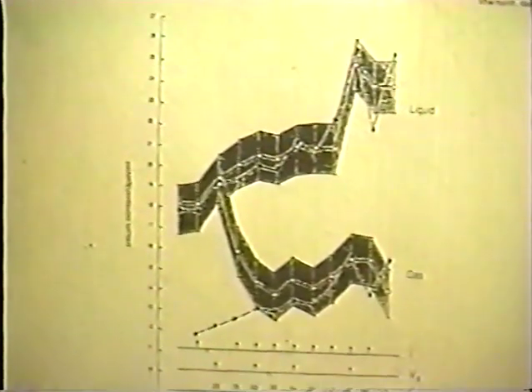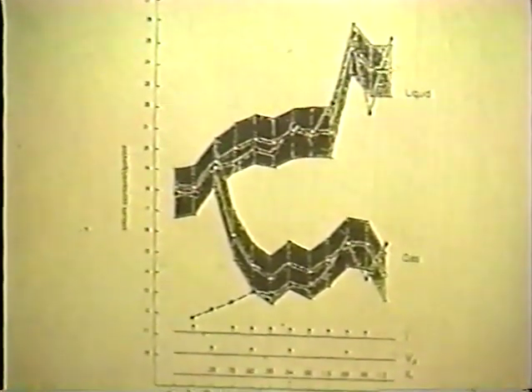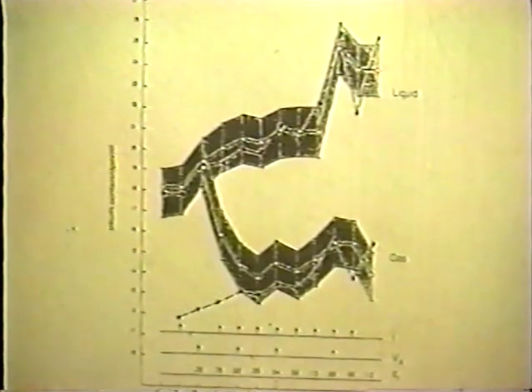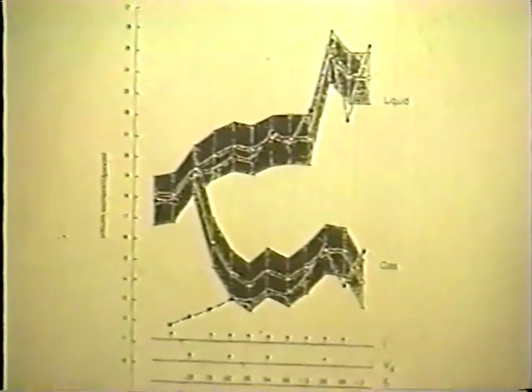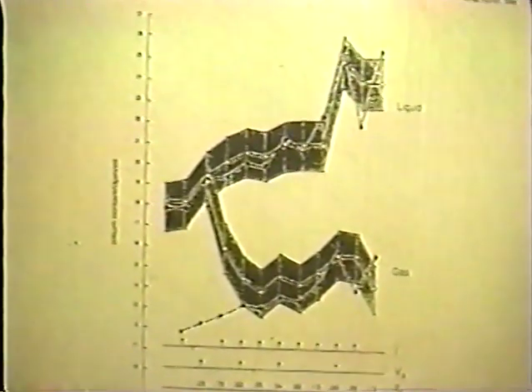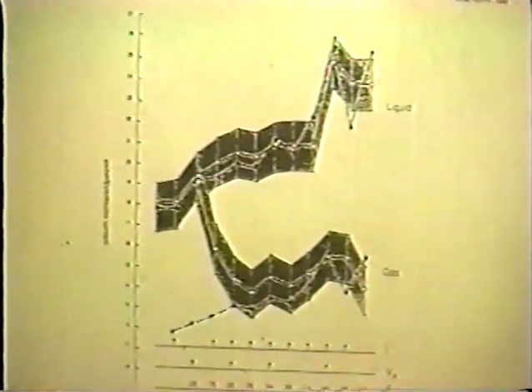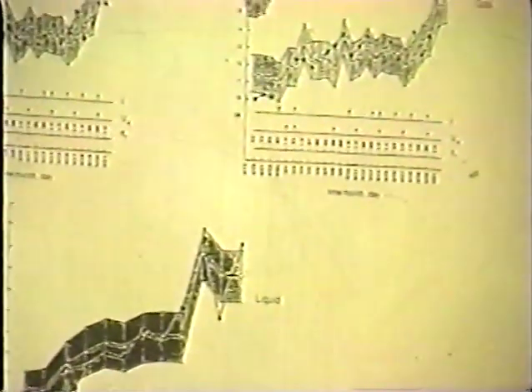In the lower region here, we have another example in which the enrichment is only in the gas phase, not in the liquid phase. That suggests that there are 2 modes of interaction between the tritium on the surface and the electrolyte. In this case, the tritium which was produced at the surface first entered the solution, and then by the usual electrolytic process was divided, as given by the separation factor S. In here, we have the opposite. First, it went into the gas phase.